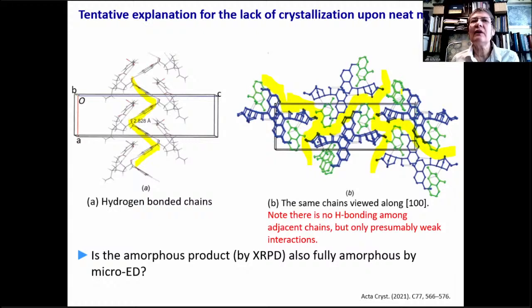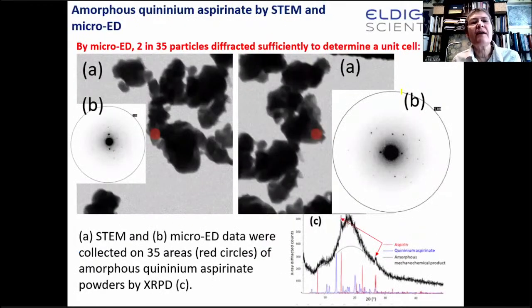So then a research question has been, is this amorphous product by powder diffraction also fully amorphous by microcrystal electron diffraction, where we can measure a diffraction pattern from individual micro particles in the micrometer size? These results are shown here, and they were done at ELDICO Scientific in Switzerland. These experiments were not done in my laboratory, they were done in Switzerland.